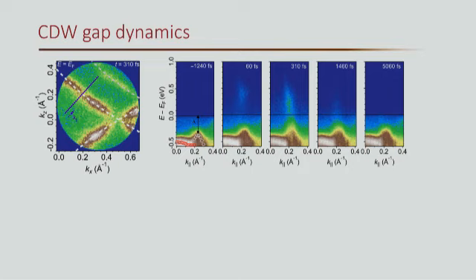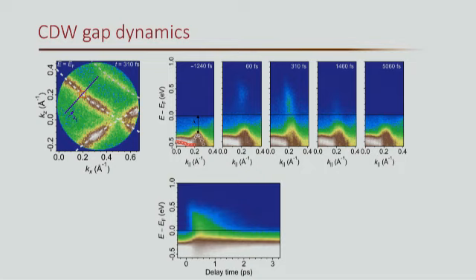So how do we extract the time scale here? We can look at this particular point where the gap is largest, and plot the integrated intensity within this momentum range as a function of time for different energies. So this is a two-dimensional plot from this four-dimensional data, where we sit at this momentum and plot energy versus the delay time. Again, we can fit, for example, the band edge of the upper band that's being populated here. And again, we see a suppression of the band from the upper CDW band, and then a quick recovery. It's not reliable to fit after about a few hundred femtoseconds because of the quick relaxation of the quasi-particles into the valence band. But we can still clearly see a trend here.